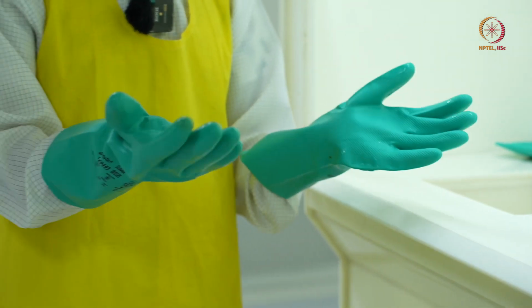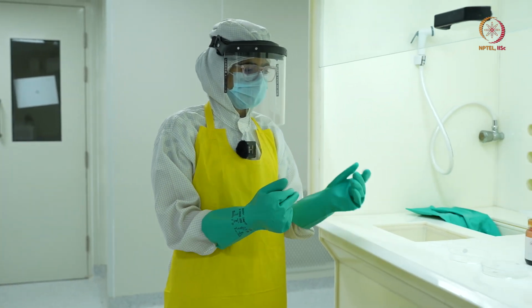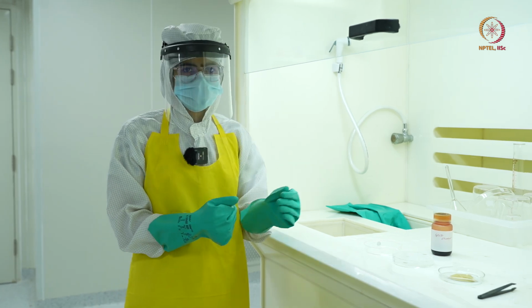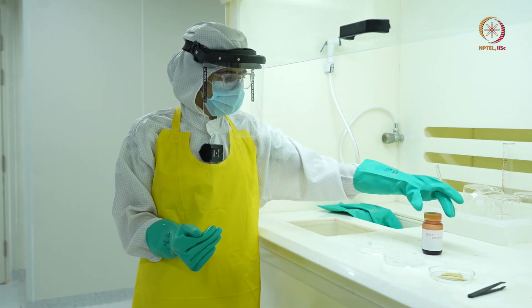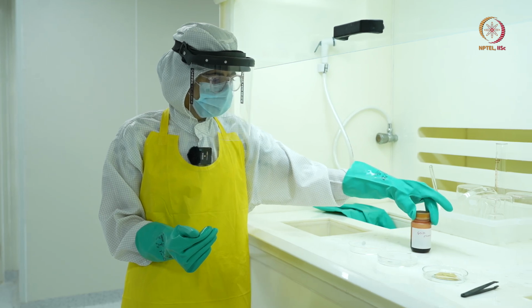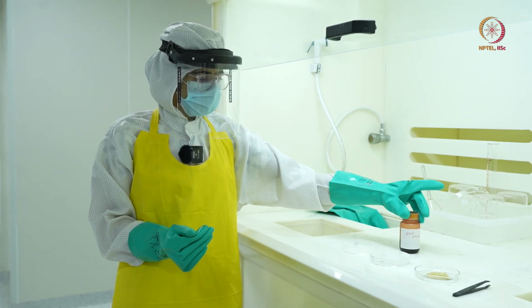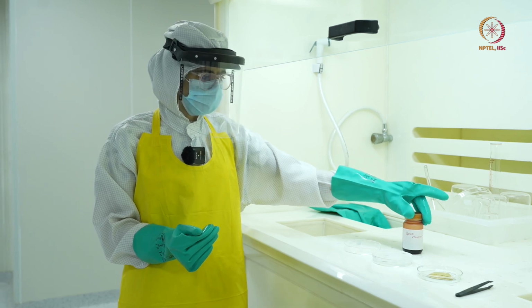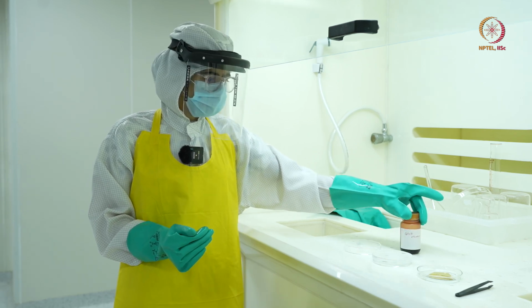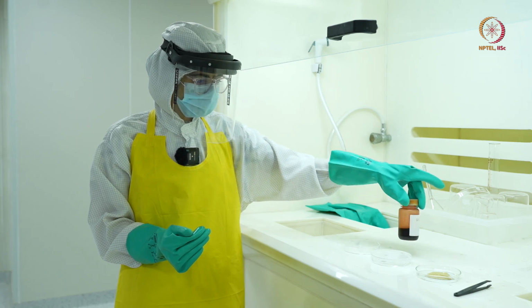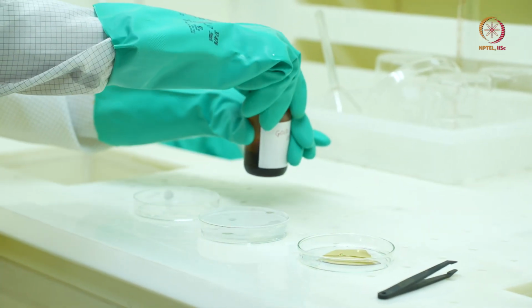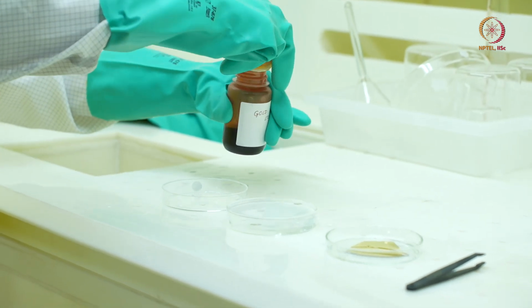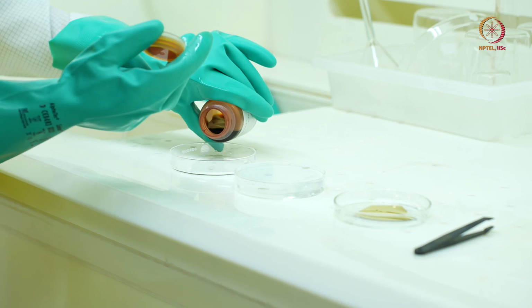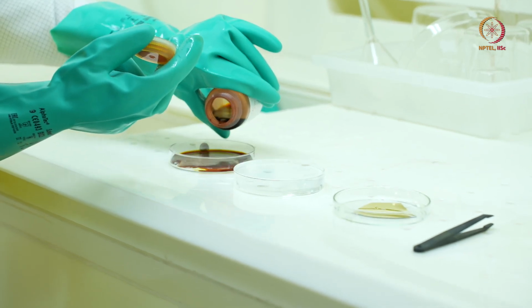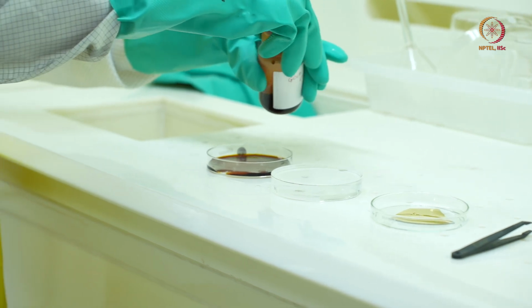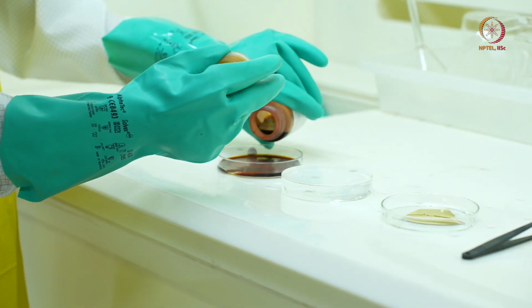So yeah, I have put on my gloves, and now we can look forward with the solution which I'll be using for gold etching. I have already prepared this gold etchant solution. It is potassium iodide saturated in DI water and one crystal of iodine. So this is a dark brown color solution, as you can see. Now it's time to pour this solution into the petri dish. So I'll take a small amount such that my sample dips into my etchant solution.